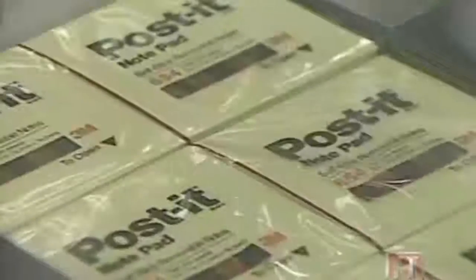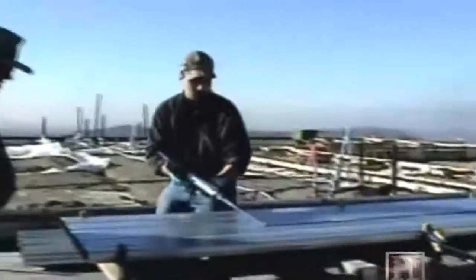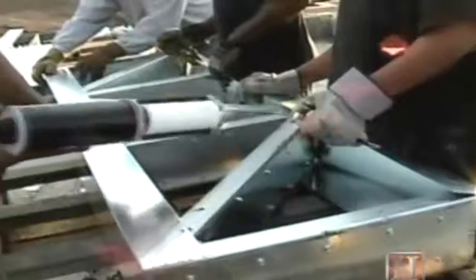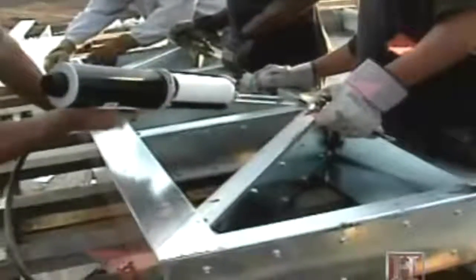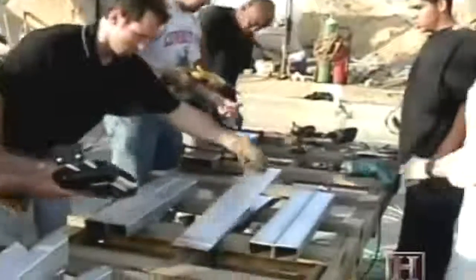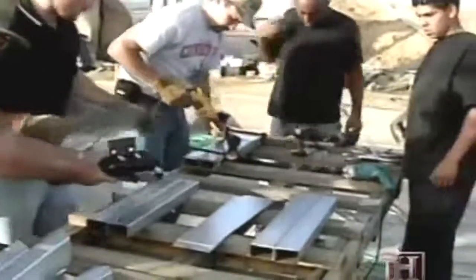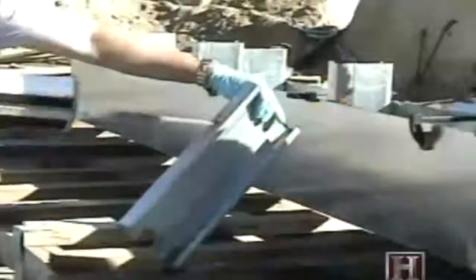A repositionable glue like the Post-it notes is a far cry in terms of strength from this construction adhesive, developed at Henkel. A reactive two-component room temperature curing adhesive system. This glue is especially designed for galvanized surfaces. When subjected to thousands of pounds of pressure per square inch, the steel will tear before the glue fails.